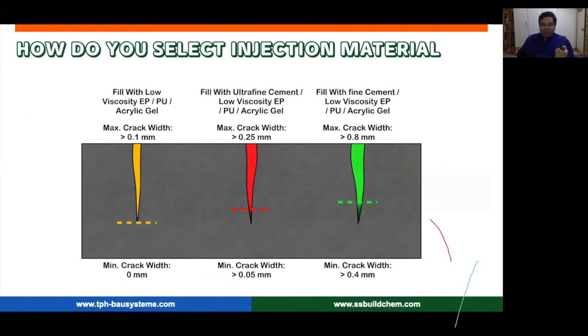Very simply put, it is based on the crack width. The more the crack width, the coarser the material you can use. So for bigger crack widths, you can use cement-based systems. And as the crack widths get finer, you have to use low viscosity epoxies or PUs or acrylic gels and so on.